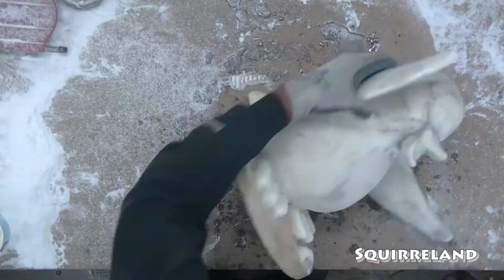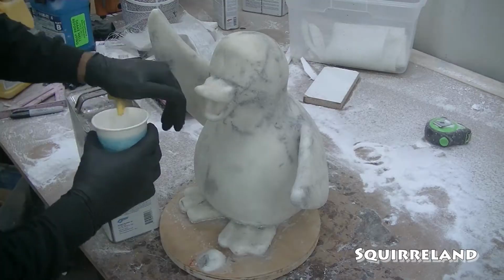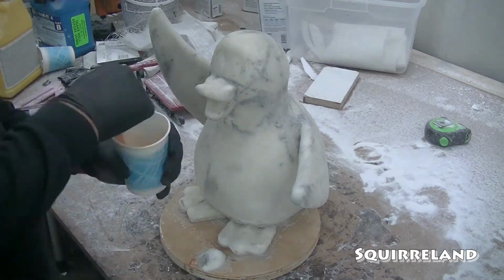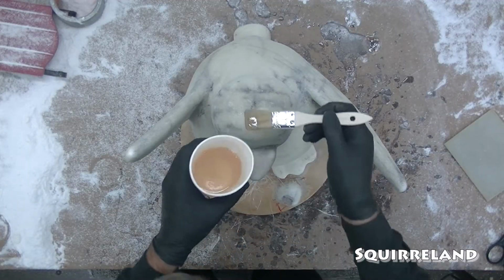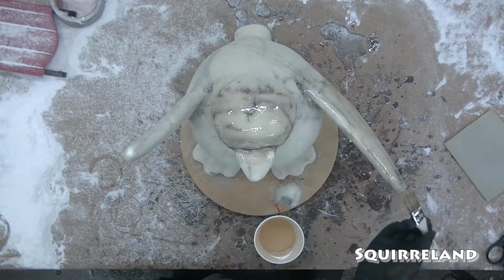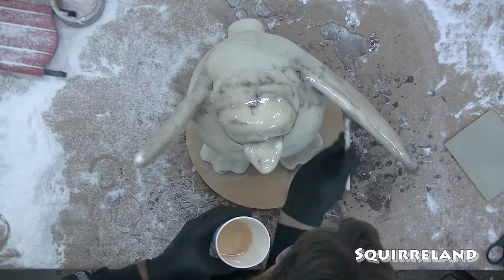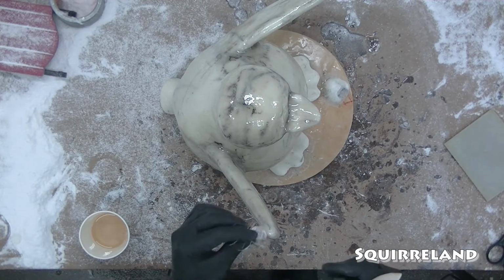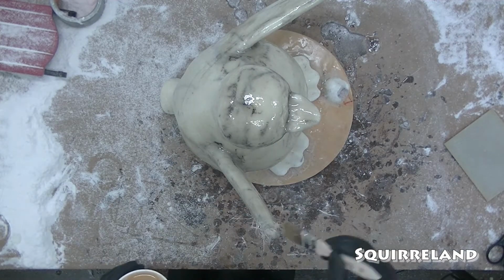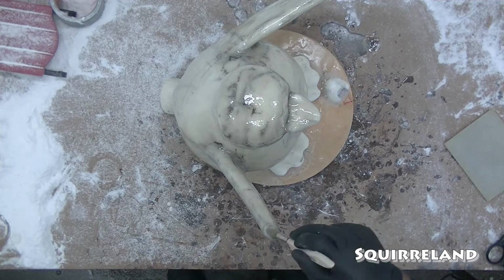With the entire sculpture smoothed out, I apply a coat of resin with no fiberglass cloth. I'm going to do this a couple of times, and in between coats of resin I'm going to sand down the high points over the whole sculpture. This will hopefully result in a smooth final surface. The tips of his arms didn't get coated in fiberglass cloth very well, so I used some rolled up strands of scrap fiberglass to add extra strength to them.